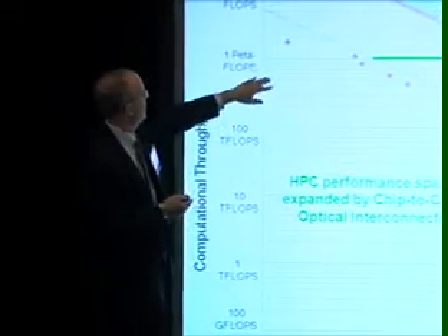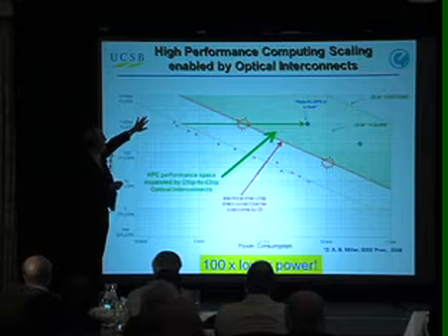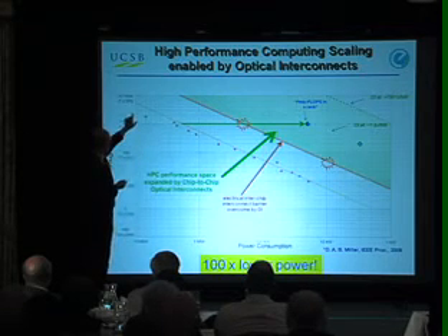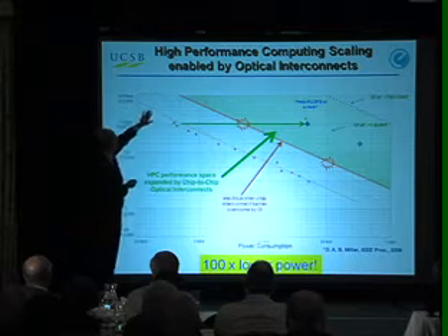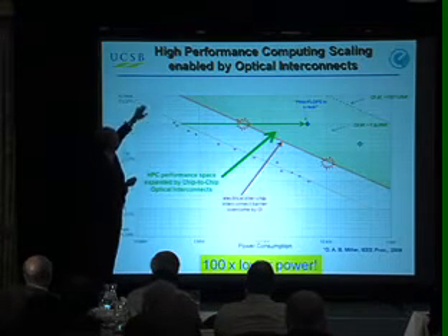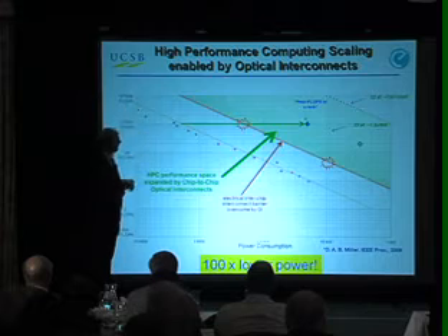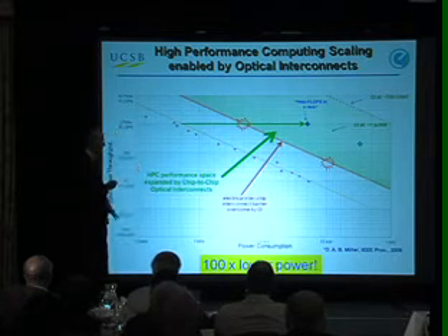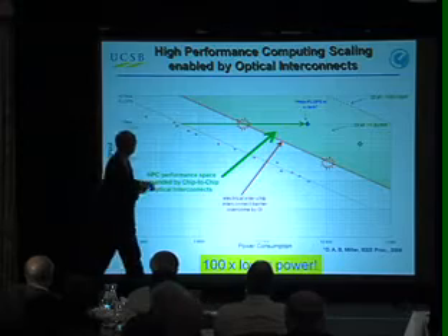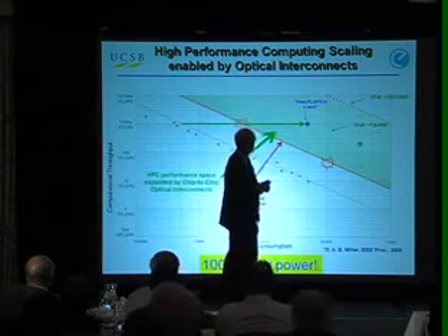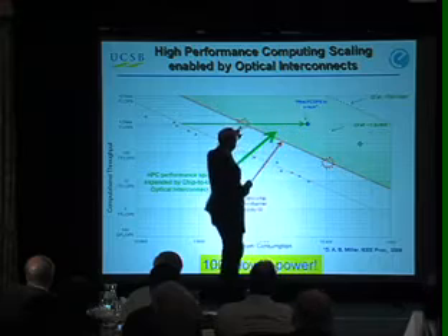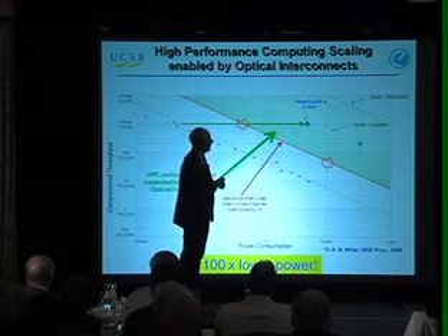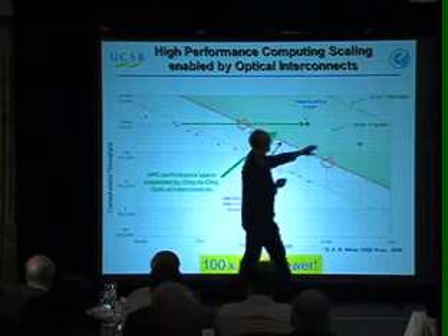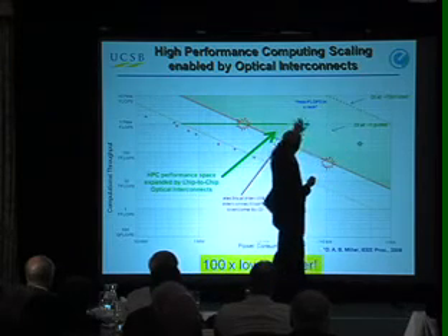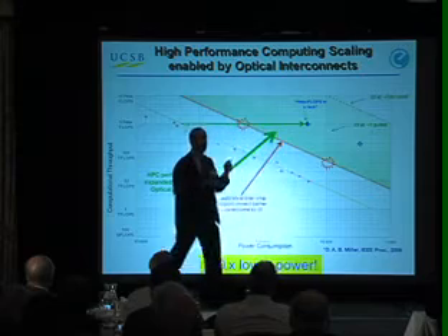These are all the world's supercomputers, or at least the top 10 or 15 computers. Here's the 2 petaflop number, and higher throughput is up here. Bill mentioned we want to get, obviously, to exascale, so you want to go 50 times above this, or 10 times, 100 times above that level. And what's going this way is power. So this is bad over here, and goodness is over there. Here are all these different computers that all fit on a straight line. The point of this curve is this: if we can reduce the power of optically interconnecting these supercomputers to on the order of a picojoule per bit, it's this line right here, then we can save a factor of 100 in the power of that supercomputer.